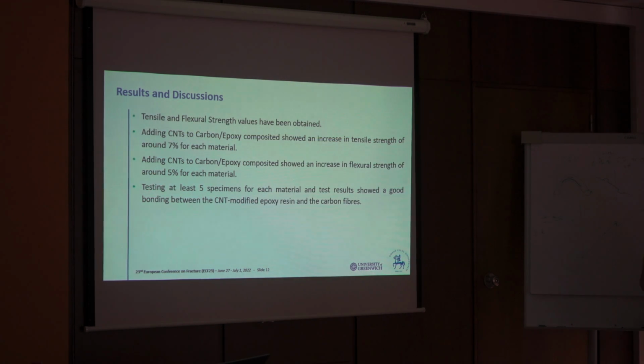So yes, depending on our study, we were able to obtain the tensile and flexural strength values, and so we can say that the tensile strength was increased by 7%, and the flexural strength was increased by about 5%. So it is still a good value, but we might need to do some adjustments according to that.